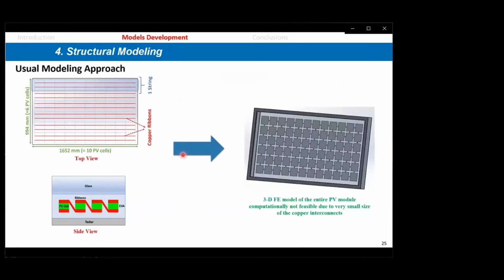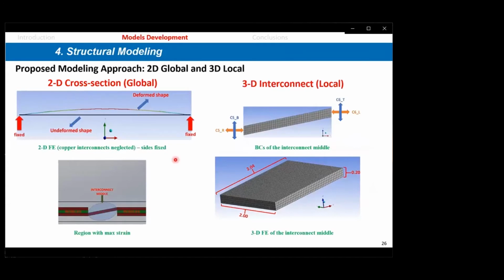Now, to perform simulations of this fatigue behavior, one can run a three-dimensional analysis, which is computationally heavy. Well, we did not go this way. What we did, we took only one string of the panel, not all strings, and we performed a two-dimensional analysis. Once we found the area of maximum stresses or maximum deflection or deformation, then we focused on that area and we used a three-dimensional finite element method. As you can see in this slide here, our proposed modeling is called two-dimensional global and three-dimensional local.